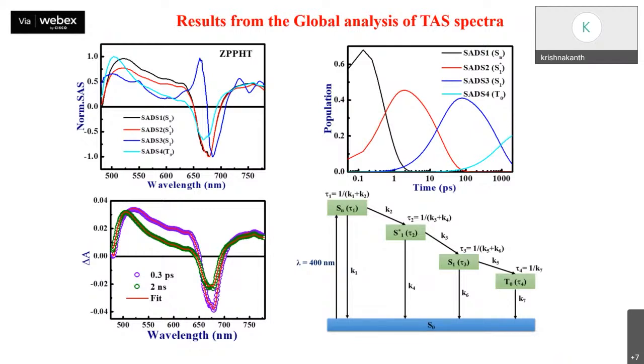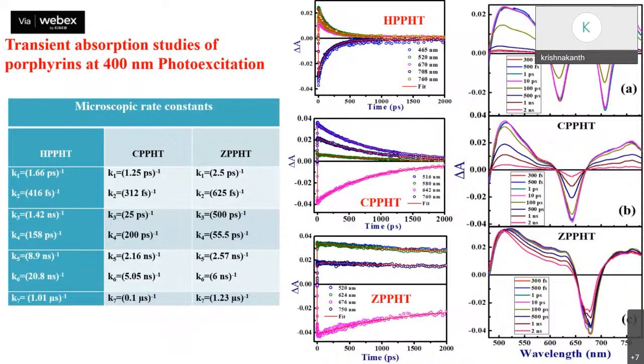This is what we have done in Glotaran software, where we use a 4-level model to fit the transient absorption spectra. So each time decay was estimated from this software. These are the parameters of the lifetimes.